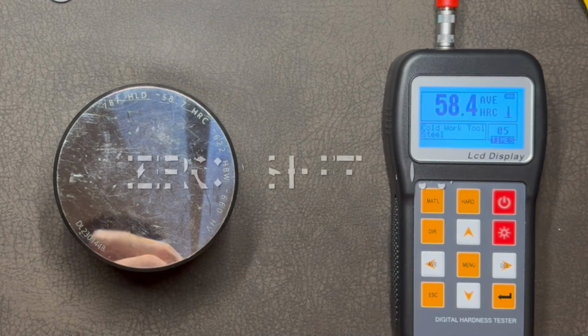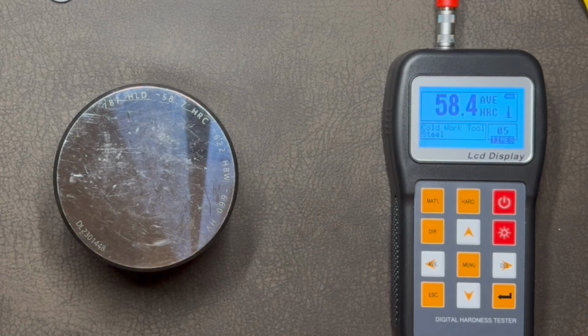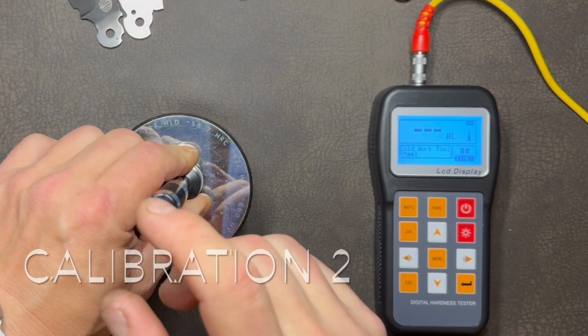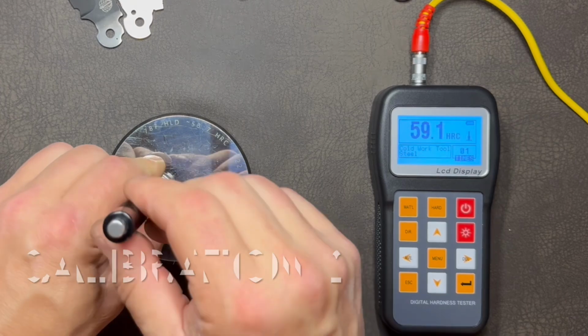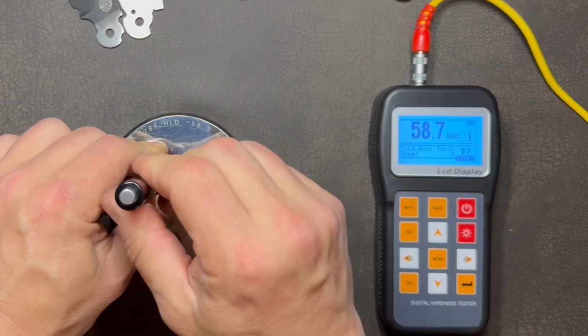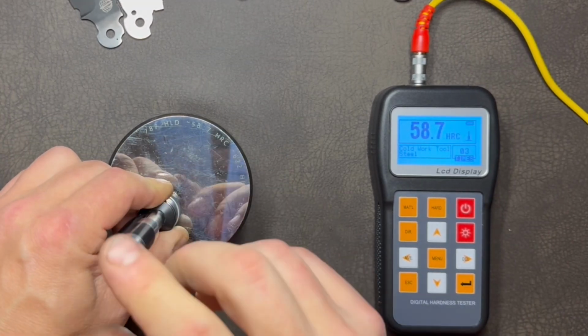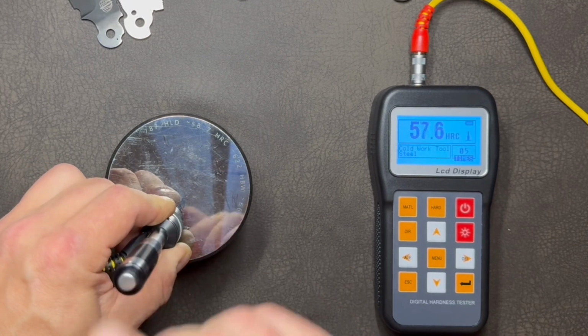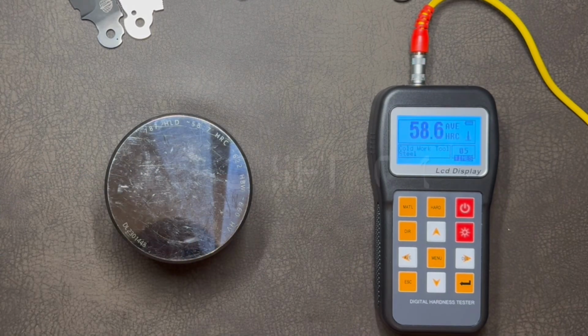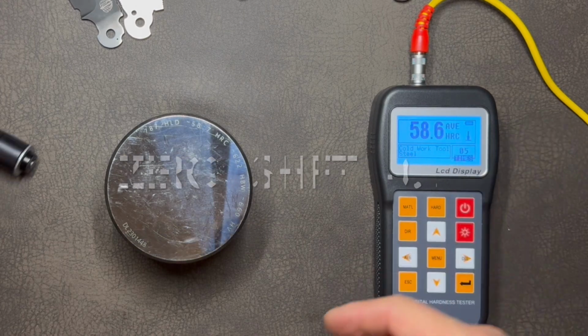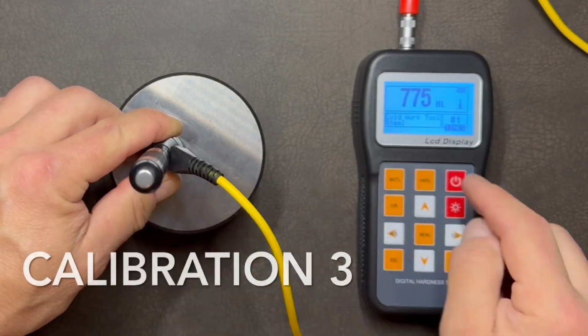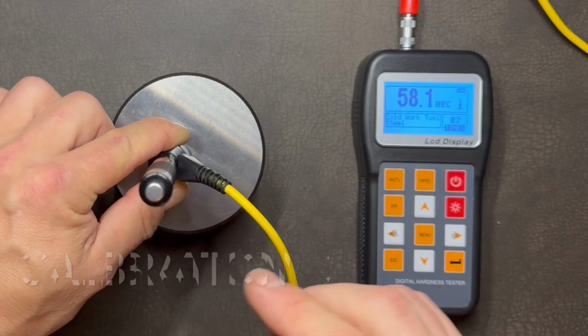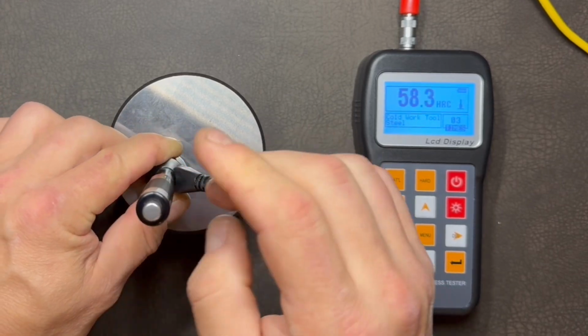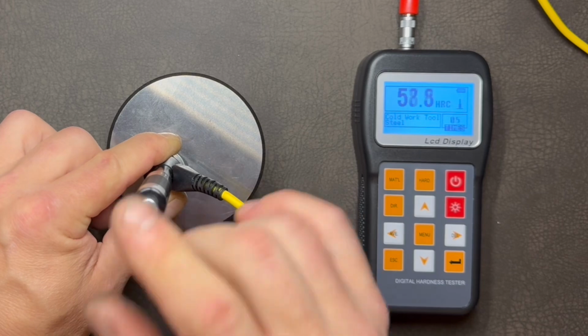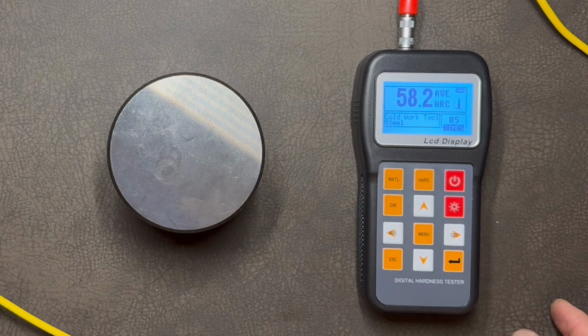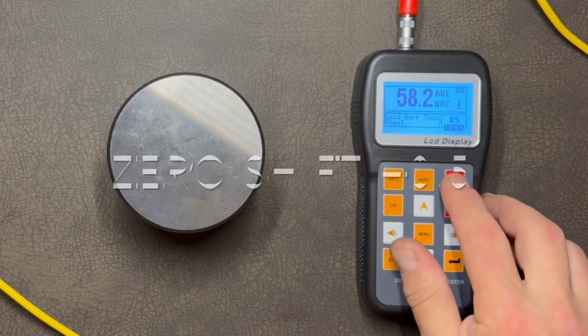So in the case of the first set, zero shift was negative 0.3 points. Then I do it one more time, 5 strikes in the next set will also yield an average, and I compare it to the nominal value. And here I only get zero shift of negative 0.1. The nominal value for this block is 58.7. So the error is anything above or below this. Zero shift for the third set is plus 0.5.